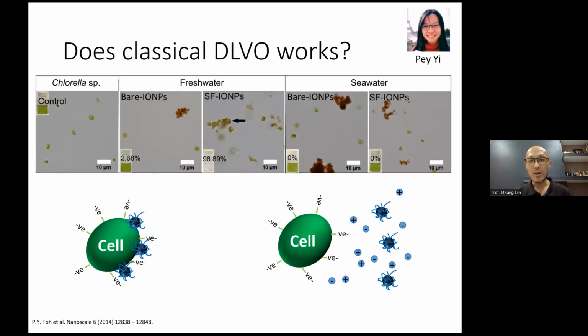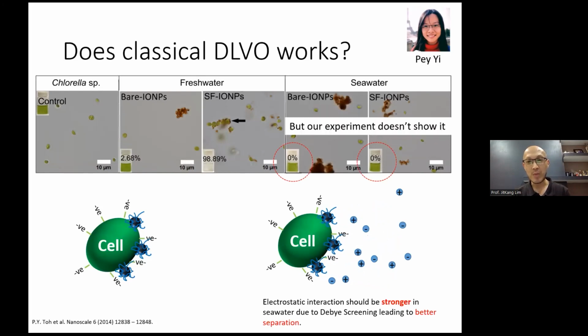In fact, if we mix them together, the bare iron oxide particles and the surface functionalized iron oxide particles, we got the same outcome, which is 0% separation. So the whole thing is this: how could this happen, right? But our experiment doesn't show it, right?